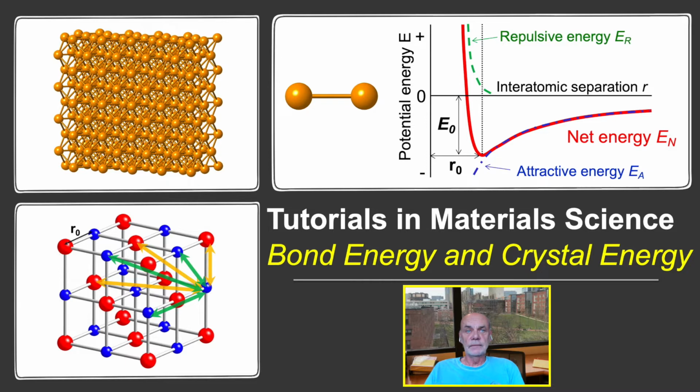of crystalline solid. Now, a mole of solid contains many bonds, and it's important that the number of bonds are counted correctly. We must also consider if it's reasonable, at least to a first approximation, to assume the bonds in the solid are restricted to the nearest neighbor atoms, or if longer-range interactions that extend well beyond the nearest neighbors must be taken into account. For ionic solids, we'll see that the longer-range interactions cannot be ignored, and we'll discuss the so-called Madelung constant and use that to calculate the cohesive energy of the ionic solid.